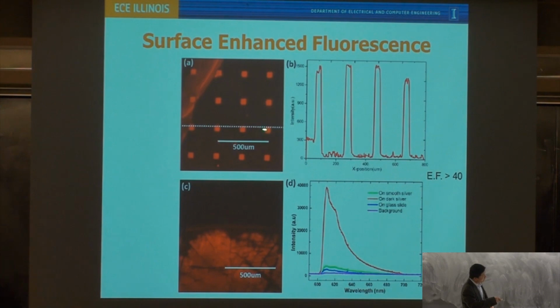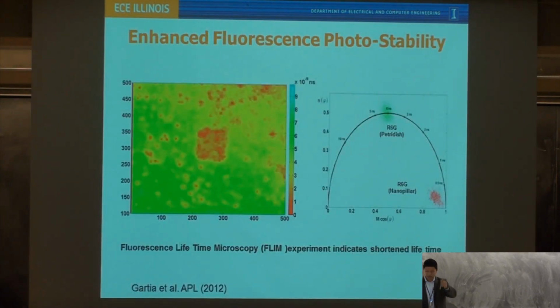If we plot the intensity profile along this line, you can see the enhancement factor for fluorescence is larger than 40 times. This is 40 times with respect to the silver film. If you compare this to the intensity on the glass slide or petri dish, the enhancement factor is even higher.